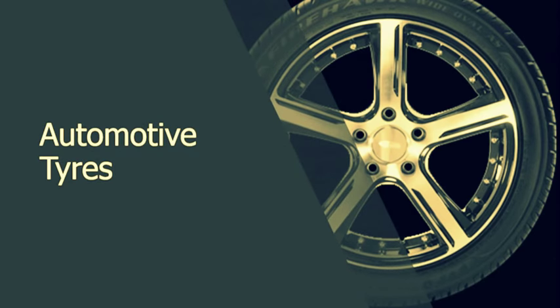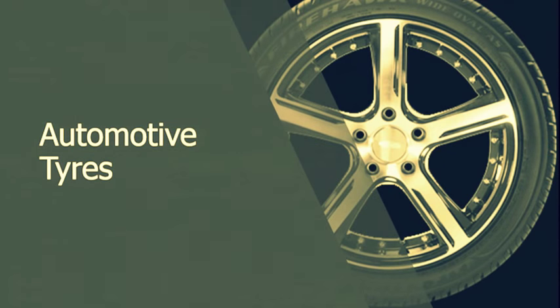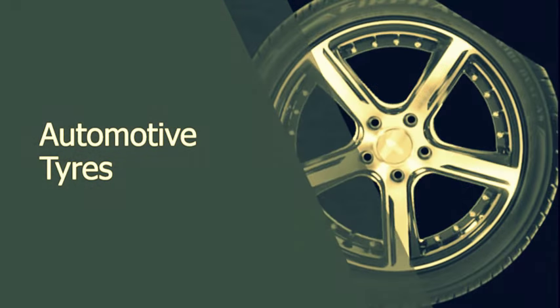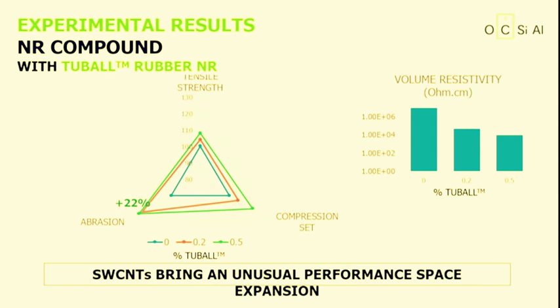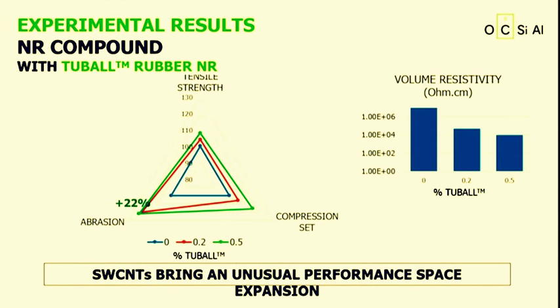Now some additional results in NR, SBR, particularly for automotive tires. This might come as a little exciting. These are the experimental results that we got in NR compound by using Tuball. In the middle of the radar plot, the middle point you see, that is the standard reference, and then there are two more triangles to it. One is with 0.2% and the other one is with 0.5%. There was a significant improvement seen in abrasion resistance. Tensile strength also increased and compression set also increased. So there was an unusual performance space expansion by using single wall carbon nanotube.